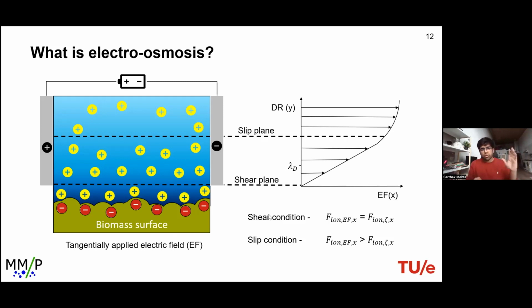As we start stripping off these ions in an electric field, we see that there is a shear plane. This means the tightly bound ions, while moving with the electric field line, cannot necessarily break the attractive force between the biomass surface and the ion present in the diffusive region.